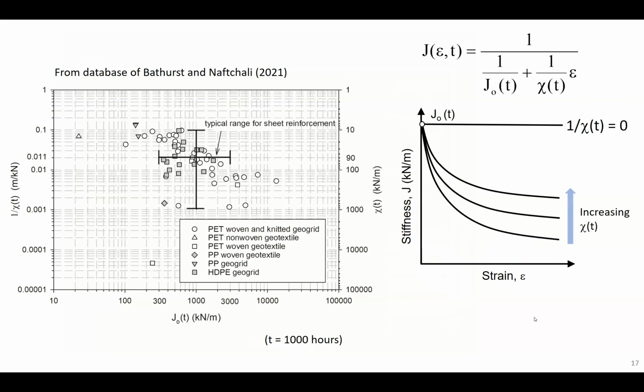We have collected this data, and some interesting summary plots have emerged. So for example, on the left-hand side, you can see data points for the values of J naught and chi for an isochronous time of 1,000 hours. On the right-hand axis, we're plotting these values directly. Sometimes it's convenient to invert this parameter so that when it is infinitely stiff, it approaches a value of 0. Now, most products have a curvature value which is positive. And what we see here is that for the same J naught term, as this value of chi t, or the inverse of chi t, changes, we get completely different shapes.